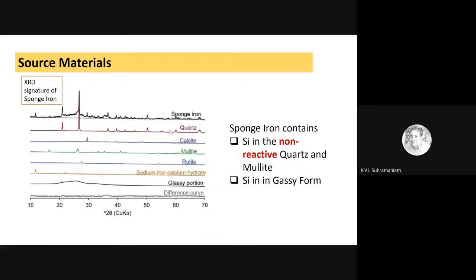Then if I look at sponge iron, even the sponge iron contained silica, but unfortunately a lot of it is locked in the quartz form, which is non-reactive. But it also has this glassy portion, which is shown by the black line, which contains reactive silica. So it does contain reactive silica, which I can use as a source of silica in my system. So these are the primary sources of elements that I can use in the cement production.